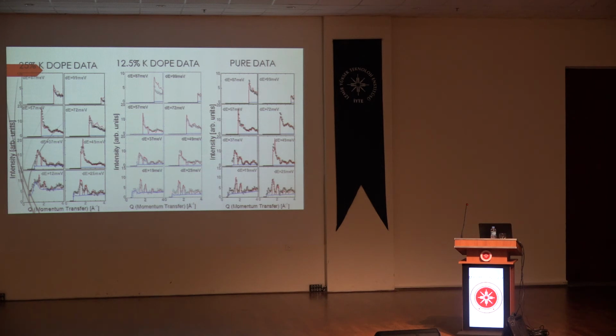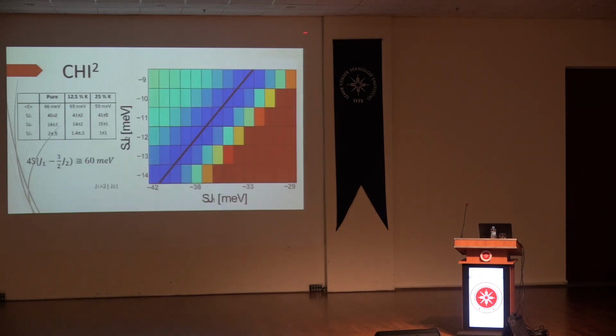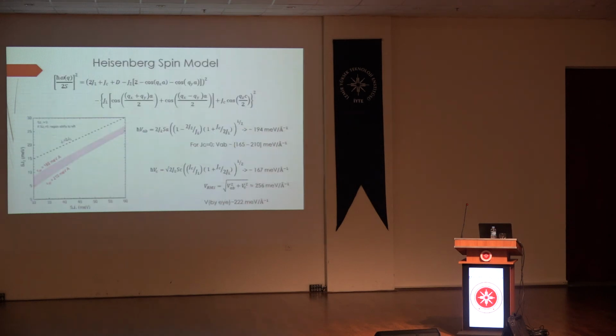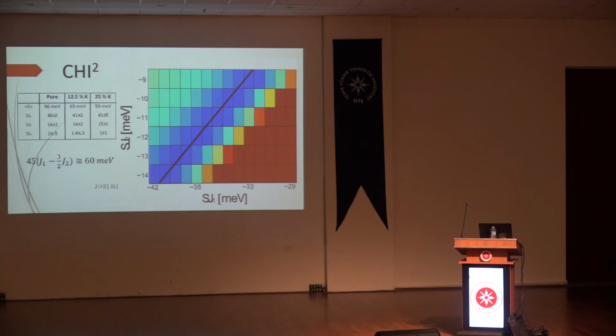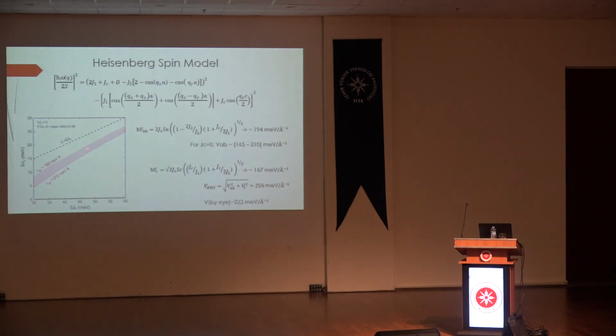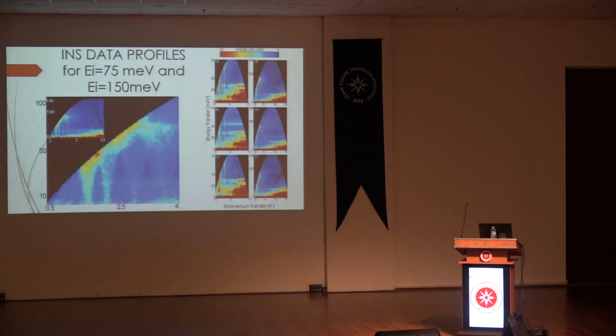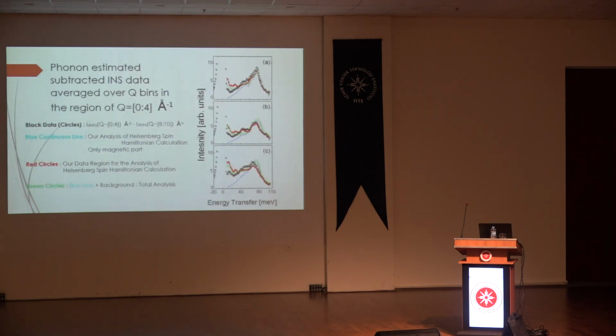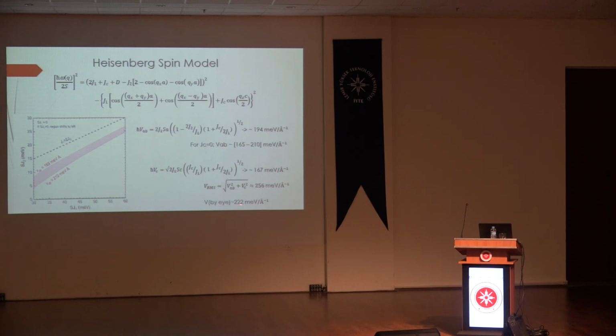There are things that we miss, that is obvious, but that is inelastic scattering, an elastic scattering, and we are the first. And this is, as you see, the chi-square best values valley. The previously published first article values are there, very close to mine. Mine is around here. And this line, when I calculate the equation for that line, basically represents, it can be shown by the spin wave values, as in this graph too. If you go and by eye take the triangular over there and get the slope to the Q values, you will get steep spin waves in the number of 222 and around. And I get this with the mean value approximation.